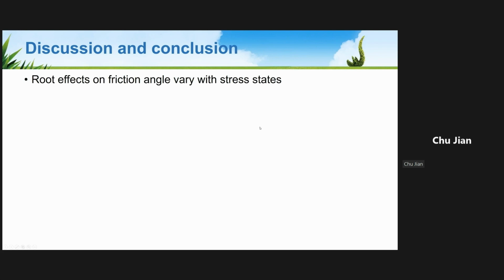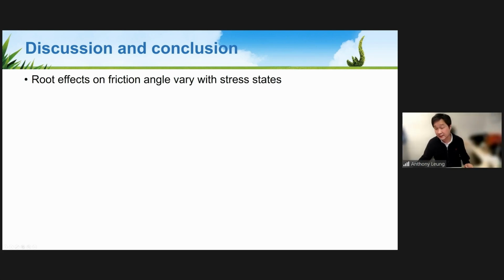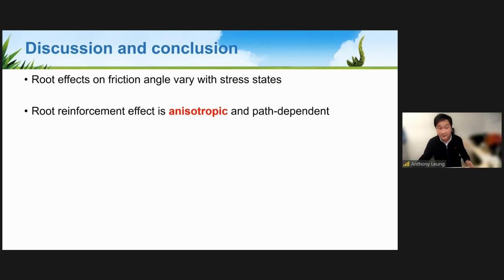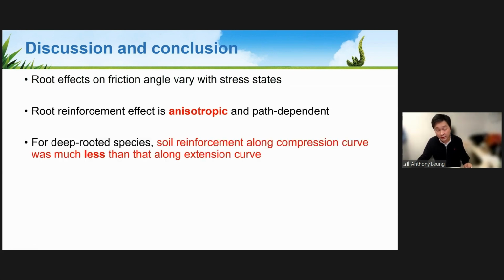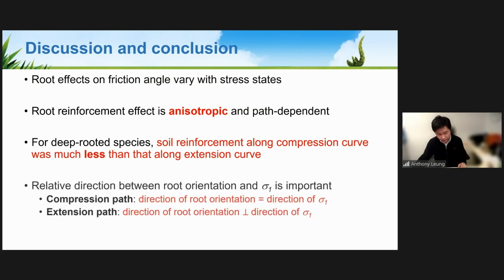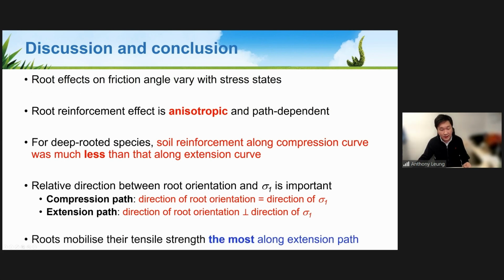So we found that roots can also affect the friction angle, not only the cohesion as typically found in the literature. And evidently, root reinforcement effect is anisotropic and path dependent. For deep-rooted species like the vetiver we were investigating, soil reinforcement along the compression curve was much less than that along the extension curve, because the major principal stress in compression is almost parallel to the root orientation for the vetiver. But if you have an extension, they are perpendicular to each other, so the root reinforcement effect will be much more significant, right? So that demonstrates the anisotropic effect. So yeah, root can mobilize the tensile strength much better along the extension path.